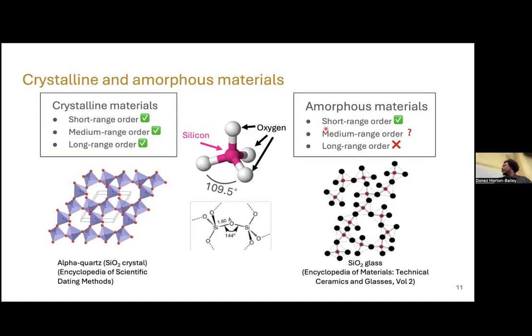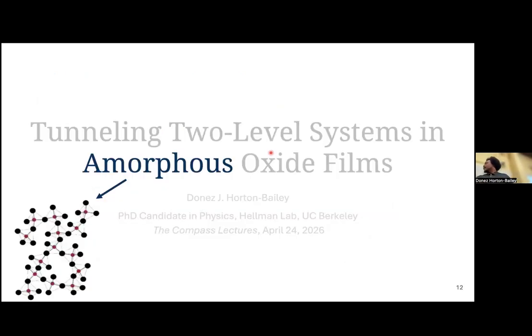For amorphous materials, we do not have this long range order. We have a more or less random arrangement of the atoms. It's not quite random in the sense that we have this underlying structure for SiO2. We have these SiO4 tetrahedra, meaning each silicon atom is bonded to 4 oxygen atoms, and that forms a tetrahedron. That tetrahedron is what is randomly arranged throughout the material. So even though the tetrahedra are randomly arranged, we still have this internal structure that doesn't go away. Despite it being an amorphous material, there is still some sort of structure in between. All right, so this explains the amorphous part of the talk.